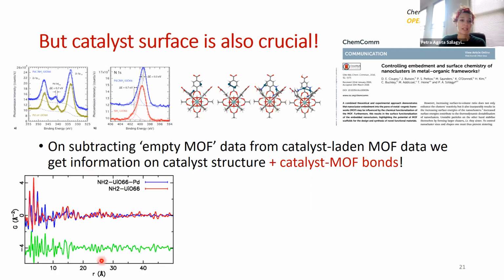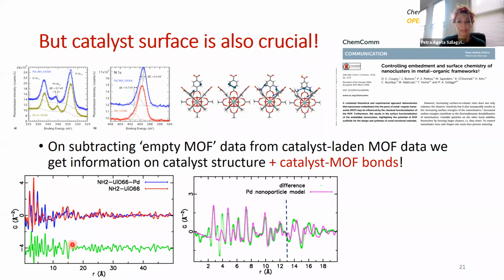So then we did the same thing as before. We collected data on the empty and the palladium-laden framework, and we generated this difference curve from it. And as you can see in pink, this is very ordered.